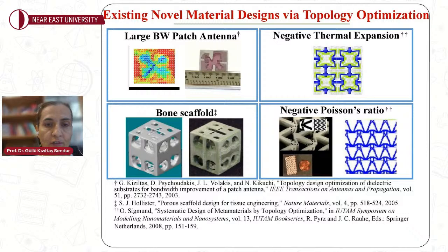In literature, this was also evidence for novel material responses such as negative thermal expansion by using two available materials, the green and blue, in space in a specific geometrical orientation, such that it would deliver you a shrinking material if subject to temperature, unlike its constituents, which would actually expand as you would intuitively expect. Negative Poisson's ratio type of microstructures were actually also a result of topology optimization schemes. And back in 2005, the group of Hollister back in Michigan showed actually that this formal technique is able to deliver optimized scaffold configurations made of a single material, and that was published in Nature Materials, the concept that this can be adapted to tissue engineering as well.